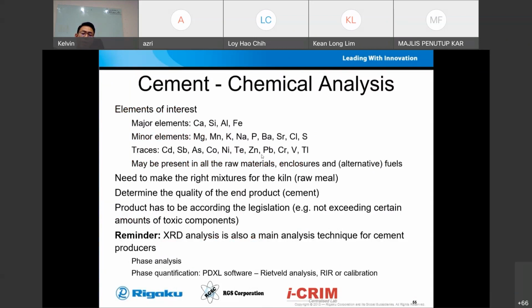Trace elements, unfortunately, are not very much available on the UKM machine. But if you are doing trace element analysis, most likely people are using alternative material. Nowadays we see a lot of the cement industry starting to use alternative materials, such as power plant fly ash as a substitute for the day-to-day raw material, or garbage which, after being sent for power plant burning, is also used as a raw material. Those raw materials need to be checked for heavy element content, and the UKM machine is also able to do this analysis.